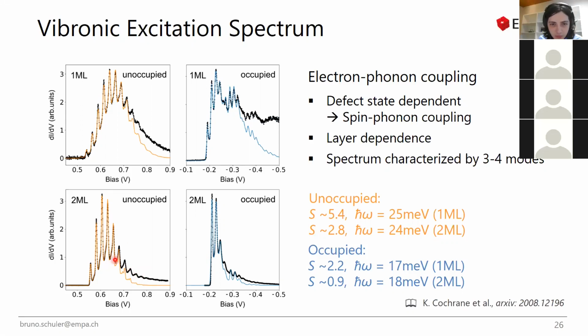Yes, so at least in our model, we are assuming a constant width. And I agree that it's probably because of the small overlap between your defect state wave function and the graphene below, which will also facilitate the tunneling of your electron eventually to the substrate. Okay, so that's probably the case.